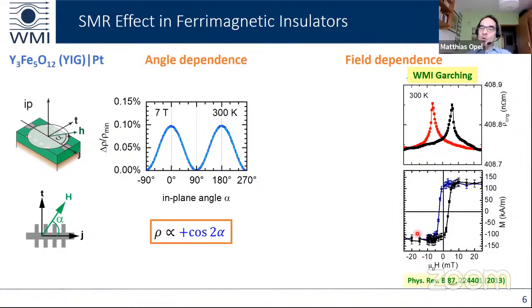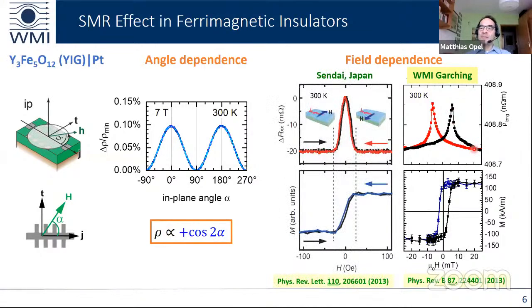And what you see in the lower graph is the magnetization of the whole sample measured by SQUID magnetometry. You see that the magnetization shows a hysteretic behavior as expected for the ferromagnetic YIG, but the resistivity also shows a hysteretic behavior which we would not easily expect from a platinum metal.